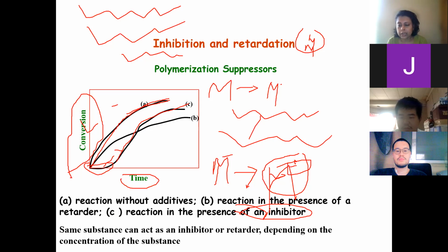Whatever it is, it happened with us many times. We had styrene stored, we thought we would take it out for the lab. After 5 years, when we took it out, it was nothing but a gel, because all these reactions had taken place inside. And if this happens, then you have to simply discard that bottle of monomer, because it is not advisable to filter out the monomer from the polymer. It is not easy to do. So you discard the bottle and place an order for a fresh bottle. So it is wastage.